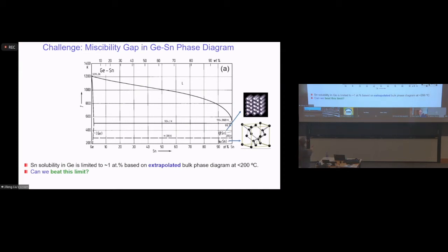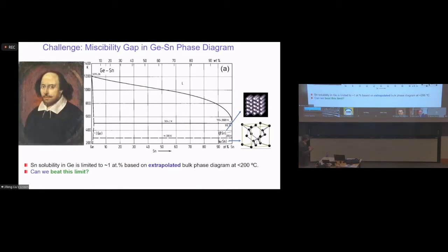Unfortunately, if you check the bulk phase diagram, it's very unpromising, because by extrapolation to low temperature, germanium can dissolve about 1% of tin, and tin rarely dissolves any germanium. So that's basically not good. You need to find some way to break through the solubility limit. If Shakespeare were looking at this figure, he would say, to mix or not mix, that's the question. Okay, but do you have a chance?